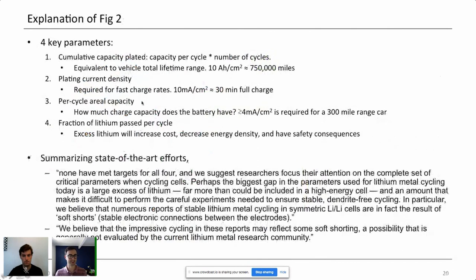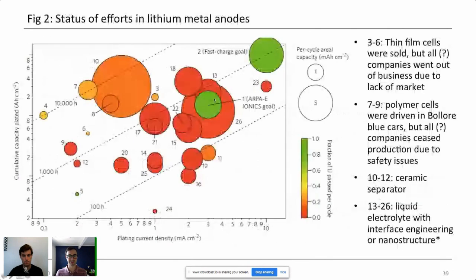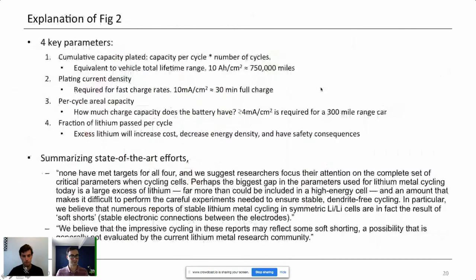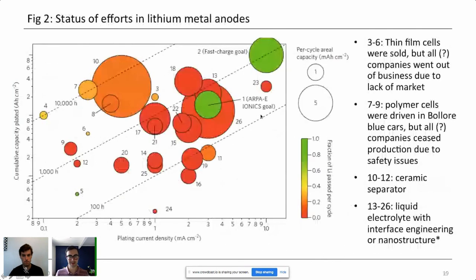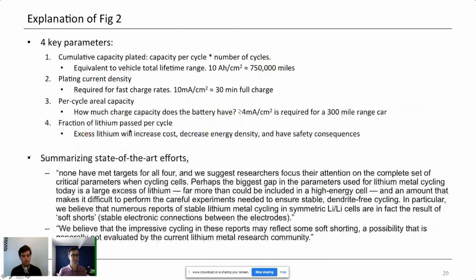In terms of per cycle area capacity, this is how large these circles are. It's how much charge capacity the battery has. You'll need more than about 4 milliamps per square centimeter to get a 300-mile range car. So that is on the sort of large circle size here. And then in terms of fraction of lithium that's passed per cycle, if you include excess lithium, that increases the cost of the battery, decreases the energy density, and as I mentioned, will have safety consequences.